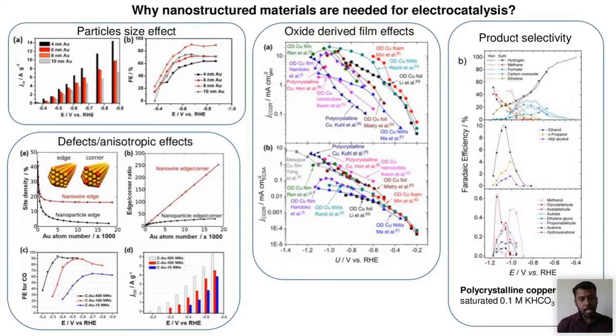For example, in the case of gold nanoparticles, there are different size nanoparticles like 4 to 10 nanometer. The black one is for the 4 nanometer. So compared to the larger particle, the smaller particle has more number of active sites and is performing well. And also Faraday efficiency can be tuned based on the particle size. And defects and anisotropic effects.